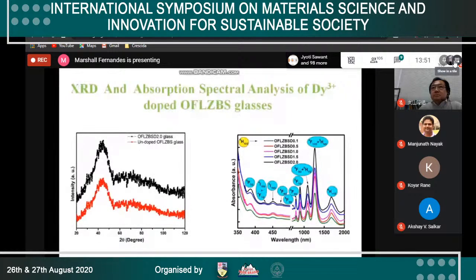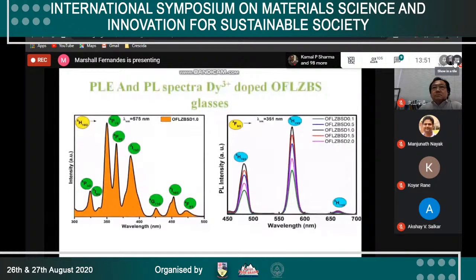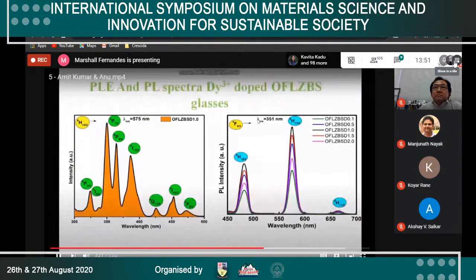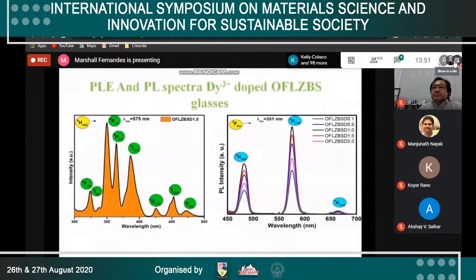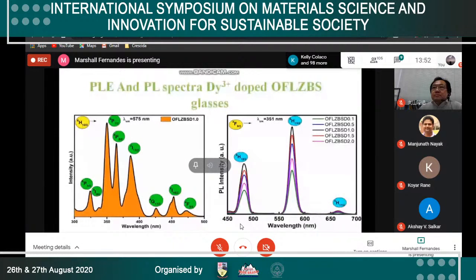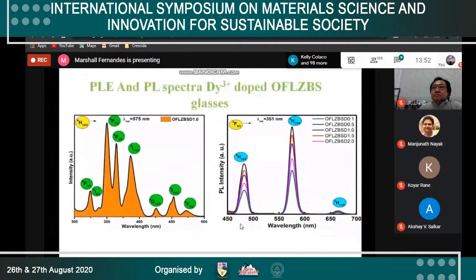Now to study the luminescence properties of dysprosium doped borosilicate glasses, a suitable excitation wavelength is needed. From the PLE spectra, we obtain an intense peak at 351 nanometers, and this excitation wavelength will be used to record the emission spectra.